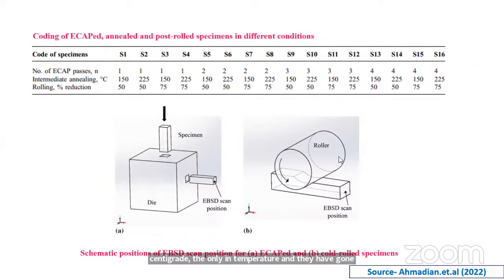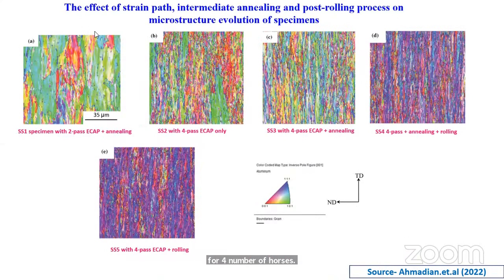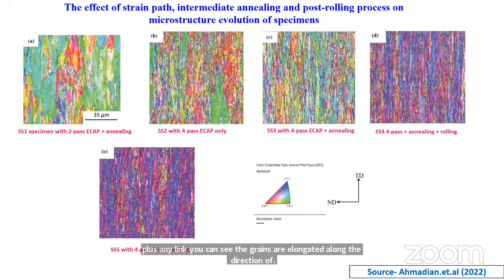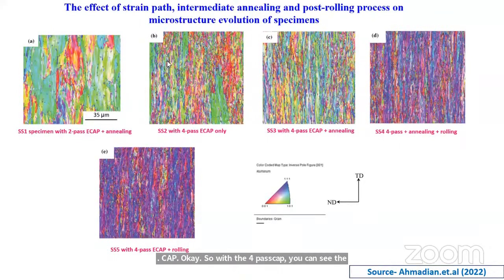Okay, so you can see these are the effects. The effect of strain path, intermediate annealing, and post-rolling process on the microstructure of the samples. The first specimen, with 2 passes of ECAP plus annealing, shows grains elongated along the direction of ECAP. With the 4 pass ECAP, you can see the grain sizes are reduced. The coarse grain structures are reduced to fine grain structures.